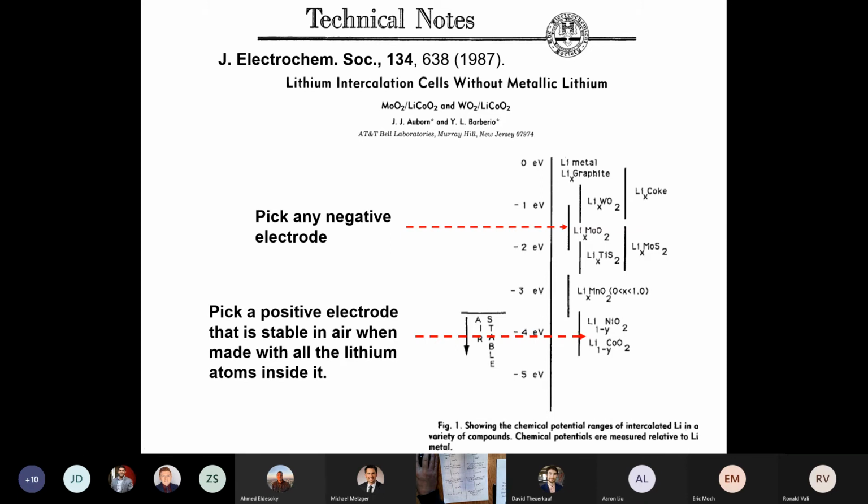Okay, so they keep the charging voltage very low. I've seen data from these cells from Medtronic. 10 years of cycling at 37 degrees C, body temperature. 10 years of cycling. Cells have lost 1% capacity. 1% in 10 years of operation at body temperature. So you can make a really long-lived cell with lithium titanate.